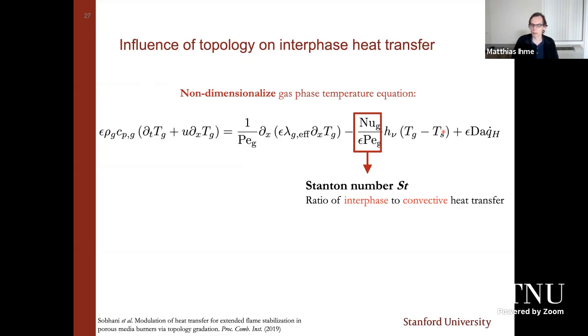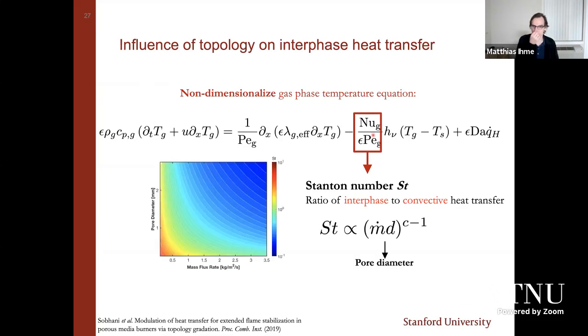Remember, very early on in this presentation, I showed you different material properties, YSZ, yttrium stabilized zirconia, silicon carbide, and alumina. The combustion performance can essentially be explained simply by this ratio of the Nusselt number to the Peclet number, right? So for conventional combustion systems or burners that I showed you in the previous result, we can show that the Stanton number is a function of the mass flow rate through the burner and the pore diameter. And by changing this, we can identify different regimes.